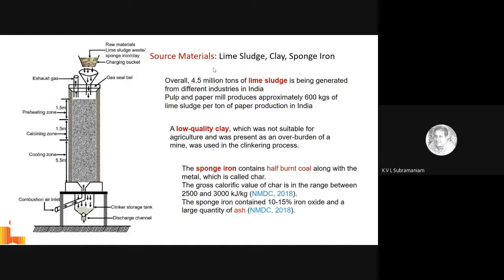And we use sponge iron. Basically, the reason for using sponge iron is it's a waste material that people are not able to utilize. It, of course, brings in iron, and we know that cement, OPC, ordinary Portland cement, contains some iron in it. But the reason for using this is because sponge iron contains a lot of unburnt coal and unburnt carbon. So we were looking to extract heat from this, and that unburnt carbon could be used as a source of heat, thereby minimizing the requirement of the coal that was required to produce the high temperature. So this was the reason for using sponge iron in the production.